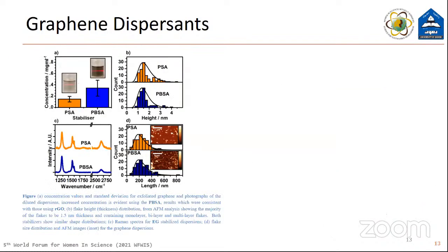So our results indicate that the introduction of a conformationally mobile spacer, in this case a butyl group, between a planar aromatic residue, which is for pi interaction with the graphene or reduced graphene oxide surface, and a polar head group, in our case the sulfonate residue interacting with the solvent, which is water, generated a molecule, which is PBSA, that was more effective as a stabilizer than the parent compound.